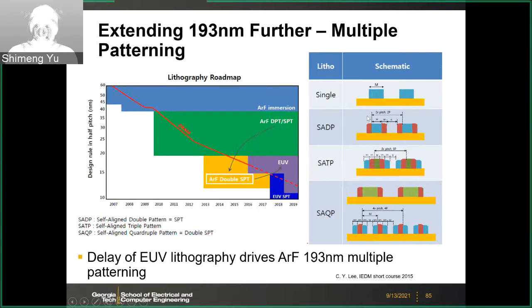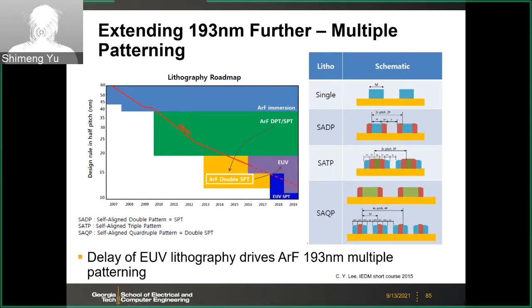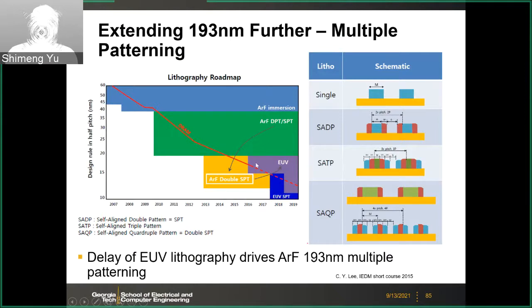You can deposit something around a mask and use photoresist trimming to grow the spacer sidewall between the mask, then use that sidewall as a hard mask to etch further. You can do this two, three, or four times — doing it four times lets you get very small features with very fine pitch. This is how you extend the lifetime of 193nm lithography to pattern features like 15 or 20 nanometers in dimension.